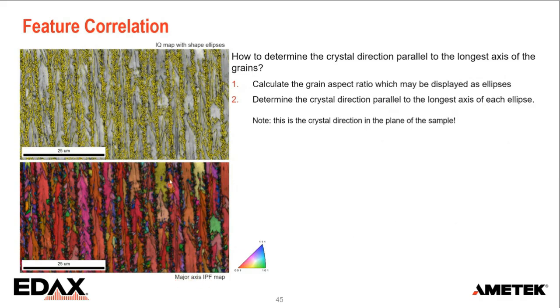And now almost all the grains are orange to red, indicating that it's the C-axis that grows a bit faster than everything else. Now, one word of warning, be careful. It's in the plane of the sample. So any sectioning that you may do, cross-section, is very, very important, will affect what you see.